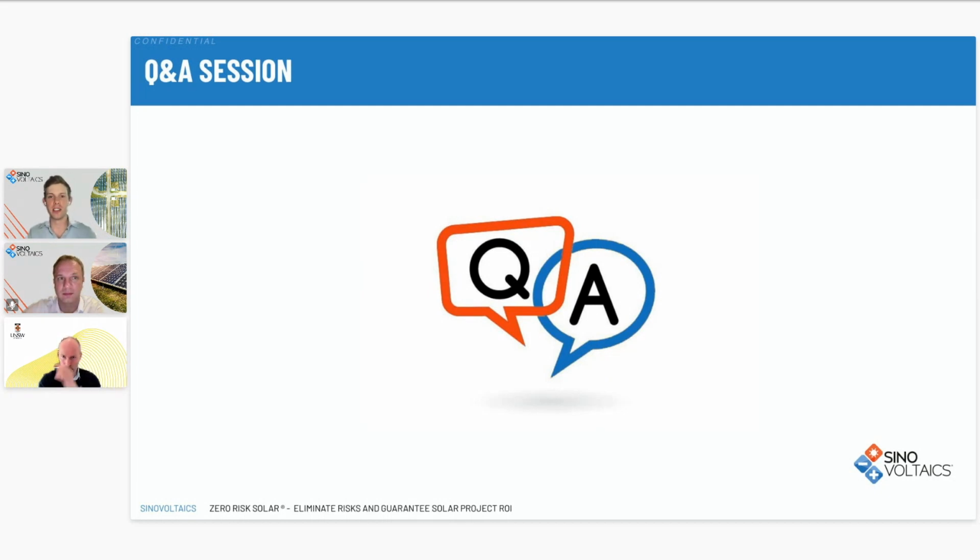All right, next question: given the rapid commercialization of TOPCon and HJT technologies, what new testing regime is being proposed to address the emerging failure modes? Yeah, that's a very good question, and it's something we're working on as well. We're involved in some of the IEC committees and SEMI committees. It would typically be multi-stress testing, because we see, for example, if corrosion is happening, the adhesion of the contact is compromised. So thermal cycling preceded by a damp heat test would make sense, or doing multiple stressors at the same time. NREL is doing some great work there, Dirk Jordan's group, and we're also working on that.